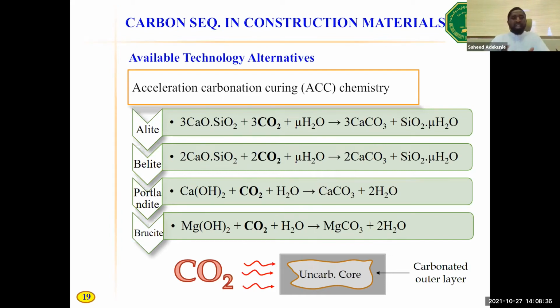So the implication of this highly dense outer shell is that it will prevent moisture from escaping from the concrete element, and that will help the curing process without you having to add moisture to cure concrete or having to apply steam as done in precast technology. And this means we can take out steam from concrete curing, and that will save some energy and save some carbon emission. And simultaneously, we are utilizing CO2 in a stable form in concrete.